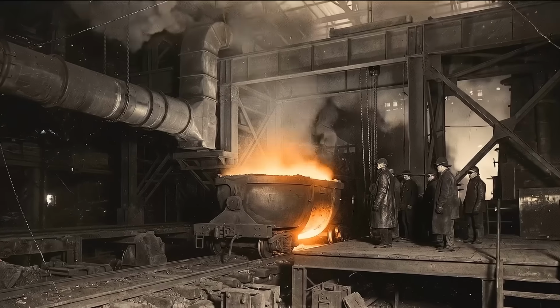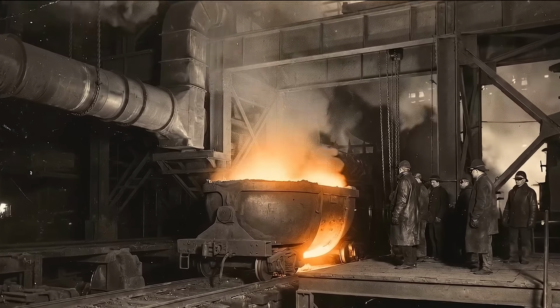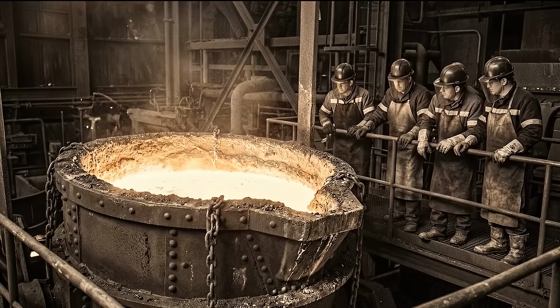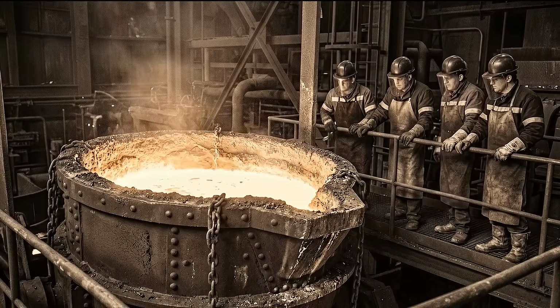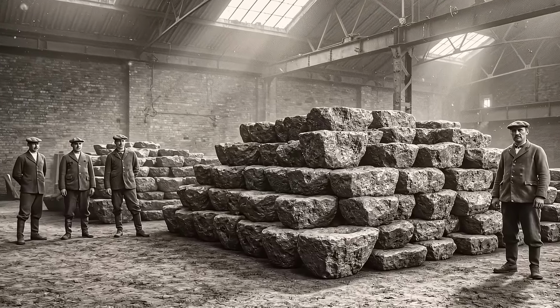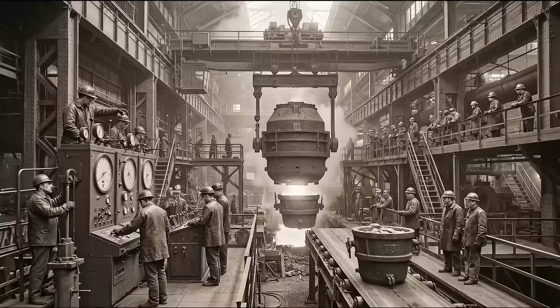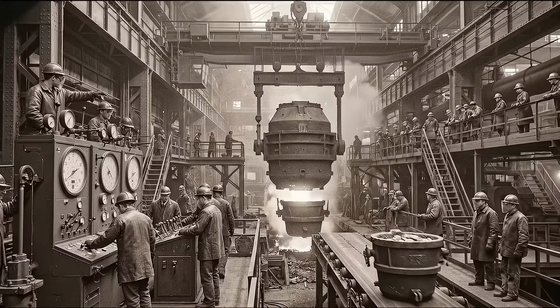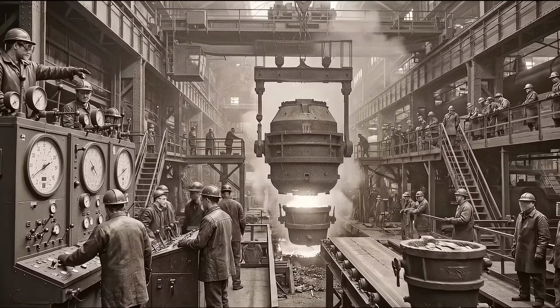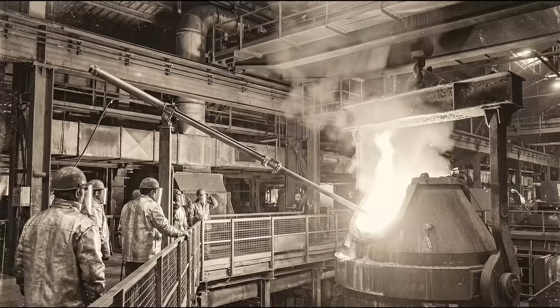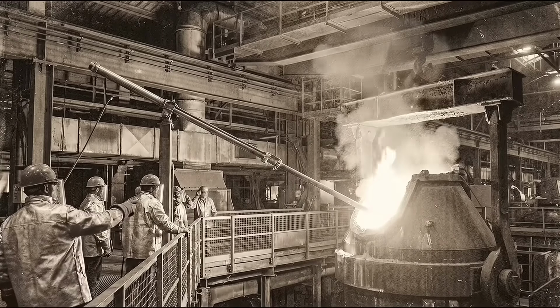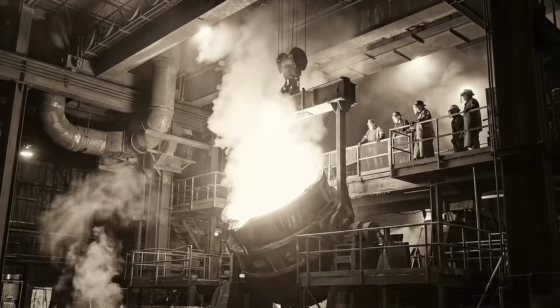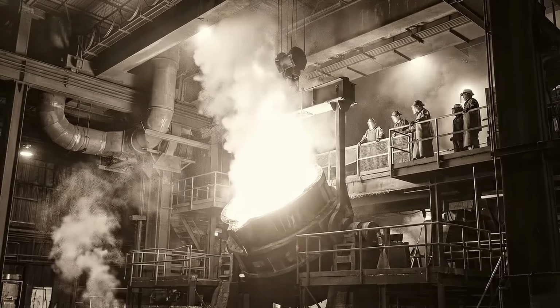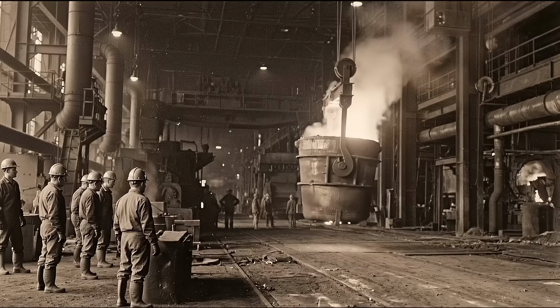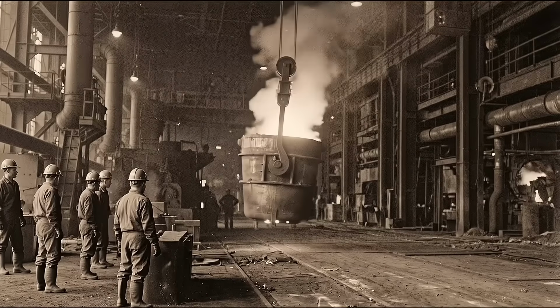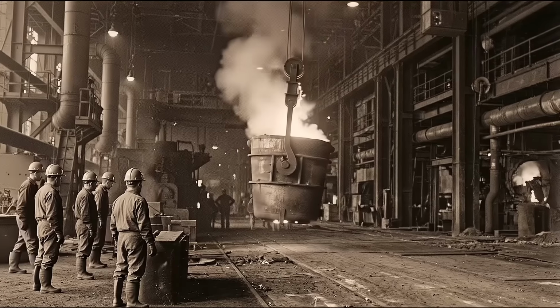The iron that comes out of a blast furnace is not steel. It is pig iron, and it is full of carbon, around 4 to 5% by weight, which makes it hard and brittle and useless for most structural applications. To become steel, that pig iron has to go through a second process, usually a basic oxygen furnace, where a lance blows pure oxygen onto the molten iron at supersonic speed, burning off the excess carbon and leaving behind a metal that is stronger, more flexible, and endlessly workable. The blast furnace does not finish the job, it starts it.